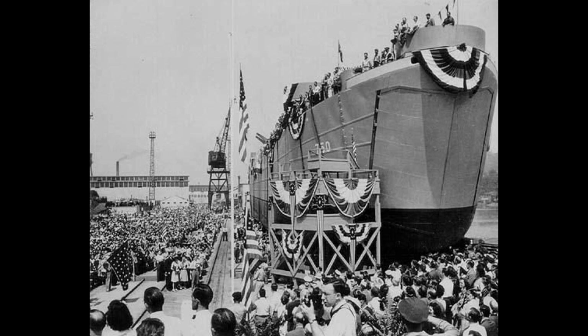On January 16, 1943, with no warning and no apparent cause, a crack suddenly appeared on her deck, propagated the entire length of the ship in seconds, and the Schenectady broke completely in two. The aft section collapsed, spilling fuel oil across the harbour. The forward section tilted drunkenly, held together only by mangled bottom plates. The newsreel footage shocked the nation. Here was tangible proof that America's rush to mass-produce ships had created floating coffins.